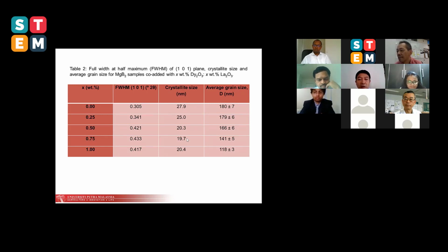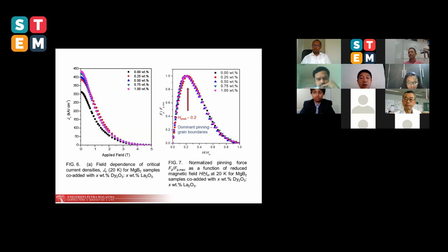The crystalline size also decreased slightly, decreasing with the increase of the co-addition amount. The main measurement for this work is Jc. We noticed that the self-field Jc has increased a lot with the co-addition of dysprosium and lanthanum oxide, especially at the 1 weight percent co-addition level, reaching a value of more than 430 kA per square centimeter. Not only that, we also noticed that Jc at applied fields, say around 1 Tesla and 2 Tesla, also increased in the samples with co-additions of dopant.